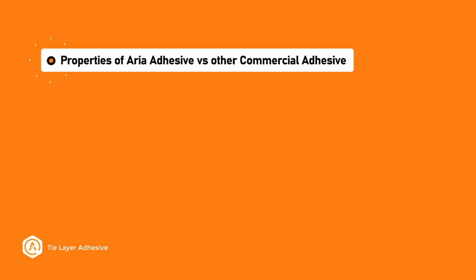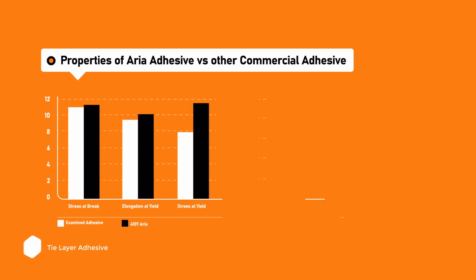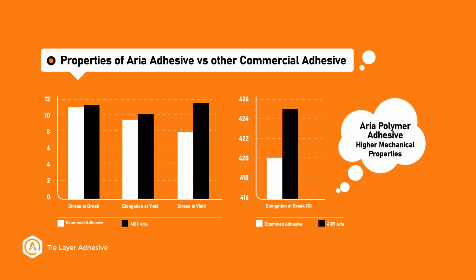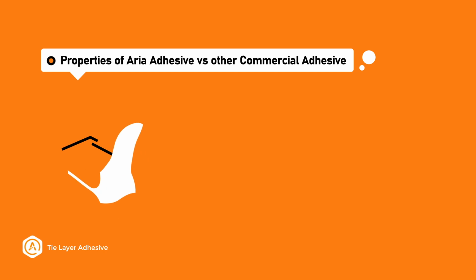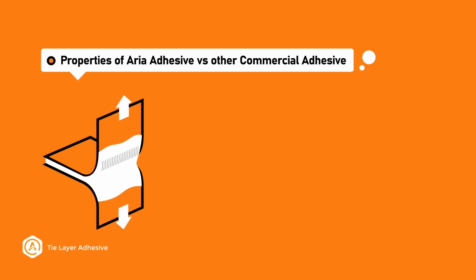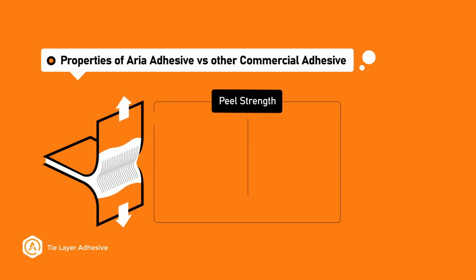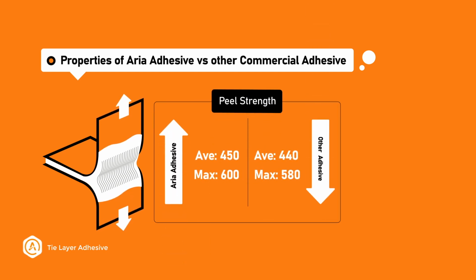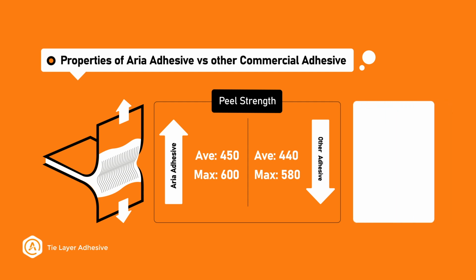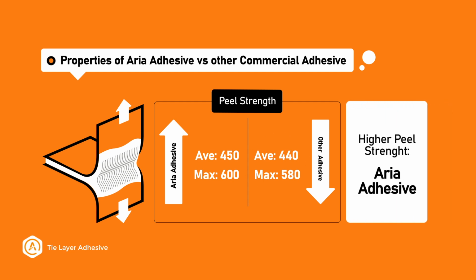What is the difference between Aria Adhesive performance and one of the other commercial adhesives? Mechanical properties are almost in a range, but Aria Adhesive 4107 has higher mechanical properties. A peel strength analysis has been done to compare Aria Adhesive and one of the other commercial adhesives. As reported by labs, Aria Adhesive 4107 has a maximum peel strength of about 600. In comparison, the maximum peel strength of the other examined adhesive is about 580.